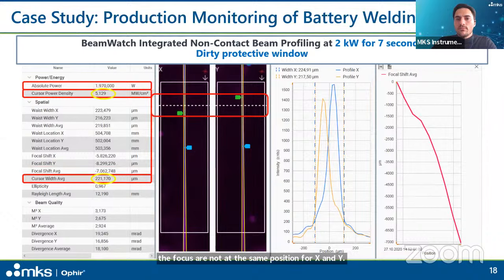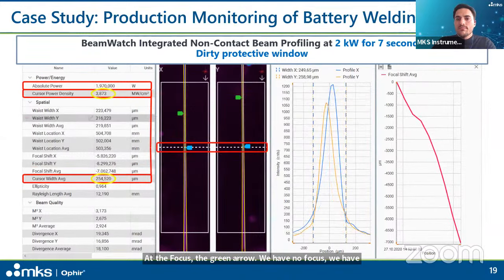At the focus, the green arrow, where the dashed line is, we now have a focus diameter of 220 micrometers and a power density of 5 megawatts per square centimeter. And at the workpiece, the blue arrow, where the dashed line is, you now have a diameter of 254 micrometers and a power density of 4 megawatts per square centimeter. Compared to the expected 95 micrometers and 27 megawatts per square centimeter, the diameter is now 2.7 times larger and the power density is 7 times lower.